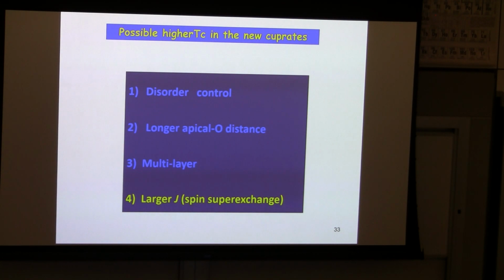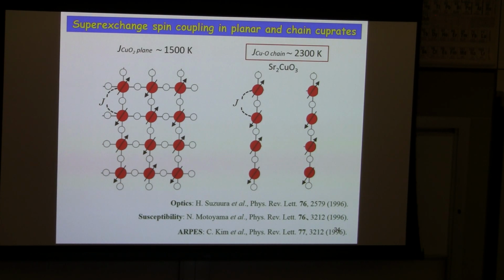I want to talk about why this oxygen deficient cuprate is so important for higher TC. One is we can expect a larger superexchange coupling constant between neighboring copper spins. You can see this fact. In the case of conventional cuprate, spins just align antiferromagnetically in the square lattice. So the superexchange coupling is very huge as compared to other magnetic material. It's 1,500K. But we know in other cuprates, specifically the chain cuprate, the superexchange coupling constant becomes much higher than two-dimensional cuprate.